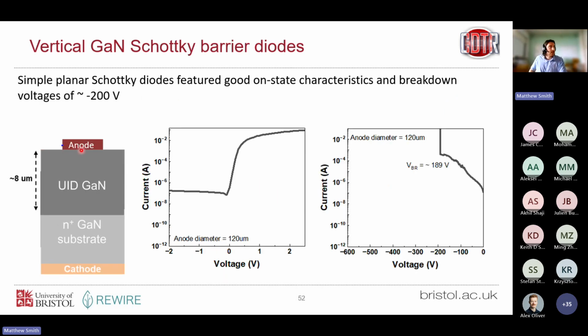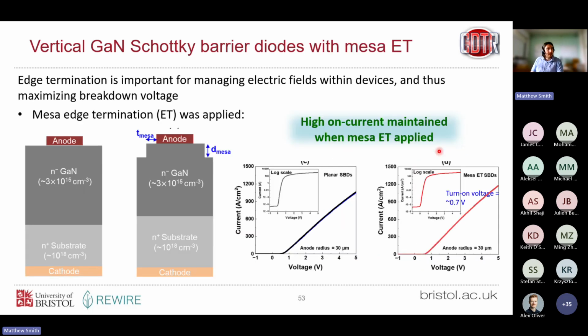So initially we looked at just planar Schottky barrier diodes, so just cathode on the back of our doped substrate, and then an anode contact on the top. And we found our on-state performance was reasonable, off-state performance not great, breaking down at around 200 volts. So we applied this edge termination technique, and I'll come on to what that means and why that's important in a couple of slides. But essentially what we're doing here is we're introducing this MESA, we call it, so this kind of table shape here.